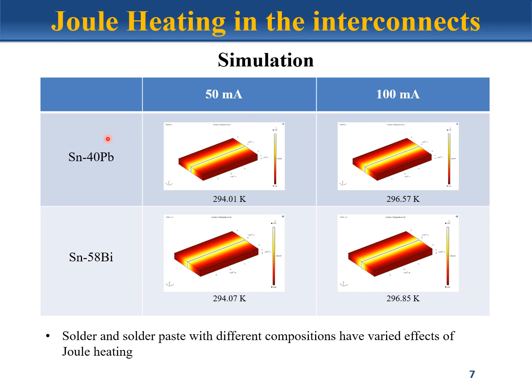So after we assign different materials to the domains of the structure, we can now run tests. We do this by changing the properties of the solder in there, and therefore changing the composition of the solder, as well as changing the amount of current that passes through the structure itself.